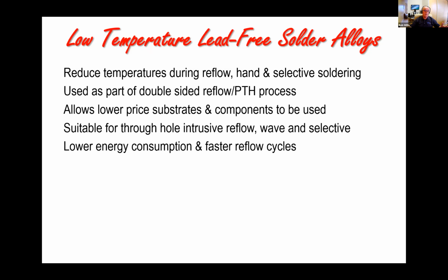Potentially lower aging, because if you think about it, if you're using copper OSP, you're using tin, which I don't like as a surface finish, personal opinion, we're reducing the effect on that for second side reflow and then through hole soldering. So that's, again, potentially a benefit.